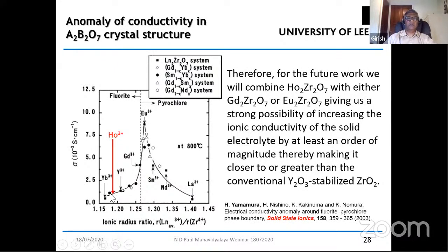So what we intend to do in the future, to increase this ionic conductivity, the logical way, is to dope it with gadolinium or europium in selected amounts, and then look at the conducting properties of the solid solution. Now we know that it does form a continuous series of solid solution, whether it is in the fluorite phase or in the pyrochlore phase. The research is already in progress in my lab, where we are doping holmium with gadolinium and europium and analyzing the conductivity results.